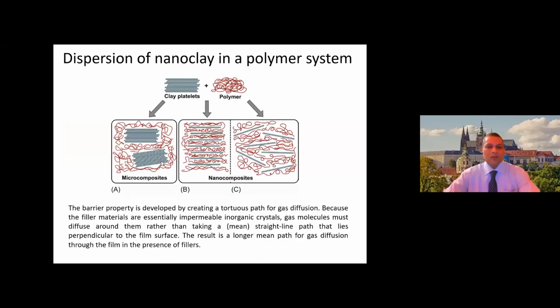One important aspect of nanoparticle use in polymers is to have very uniform dispersion of particles. Otherwise, these particles have a lot of surface charge which is not balanced, especially because this is almost at the atomic and subatomic level. So a lot of electrons are free, and this decides the polarity of the particles, and they have a tendency to agglomerate, to attract each other, create clusters. If we do not agitate rigorously, nanoparticles will aggregate to create microstructures very quickly. That is why as soon as we create nanoparticles, they must be dispersed into some solvent. So it is necessary by ultrasonic technique for long period of time for the particles or the platelets to be dispersed, scattered uniformly, and then only we can achieve the performance.